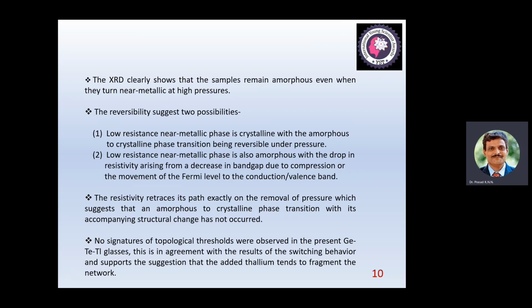So the reversibility suggests two possibilities. Number one, the low resistance near metallic phase is crystalline, with the amorphous to crystalline phase transition being reversible under pressure. Number two, the low resistance near metallic phase is also amorphous, with the drop in resistivity arising from a decrease in energy band gap due to compression or the movement of the Fermi energy level to the conduction or valence band. The resistivity retraces its path exactly on the removal of pressure, which suggests that an amorphous to crystalline phase transition with its accompanying structural change has not occurred. We also noticed no signatures of topological thresholds in the present germanium, tellurium, thallium glasses. This is in agreement with the results of switching behavior, which supports the suggestion that added thallium tends to fragment the network.